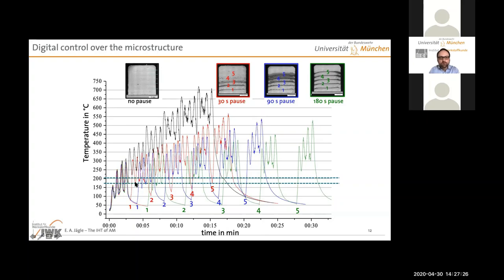Whereas if we start to introduce pause times, here in the red case, it's 30 seconds. And you see there's a little bit of cool down. And then we go up and there's cool down and then we go up. So you still have an overall thermal runaway, but it is way less. And we do get already our layers. Not at the very top though, because there the overall heat is already so high that the cooling time does not reach below the MS temperature, which is this dashed line here. And then at 180 seconds of pause, every pause is so long that you're going down to more or less room temperature after every time.